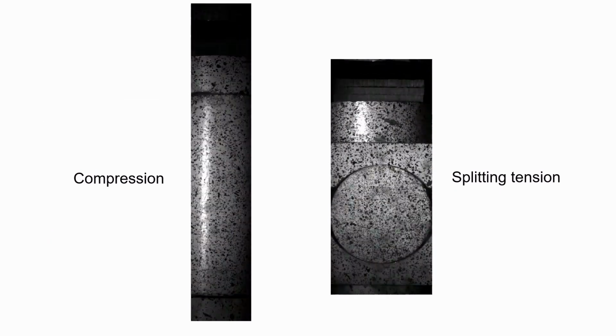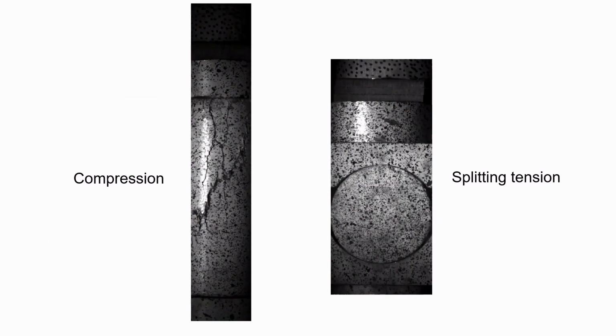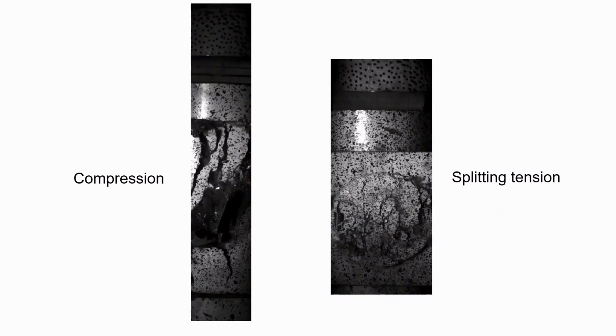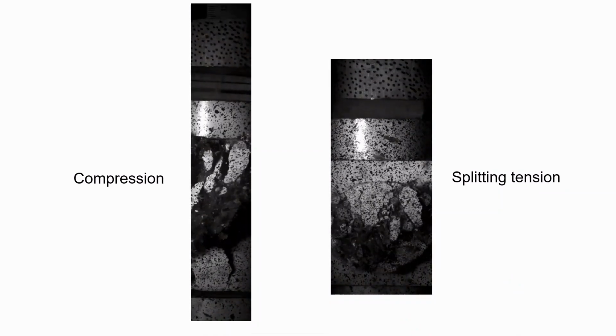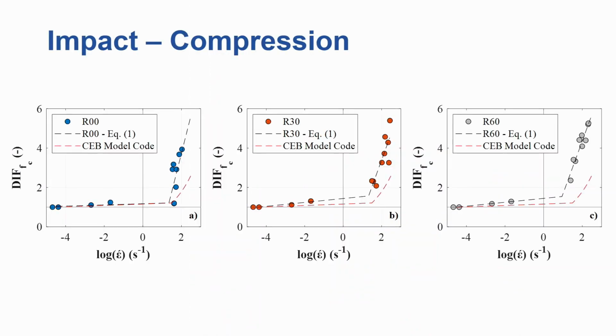And then we studied the impact response of such concrete under compression and splitting tension. And we were mainly interested in the dynamic increase factor. So this is simply the ratio of the dynamic strength over the quasi-static strength at a given strain rate. So I'm plotting here the results for R00, R30, and R60. And the dynamic increase factor tends to increase as the strain rate increases, initially gradually, and then there comes a point where it just shoots up. We call this the critical transition strain rate.